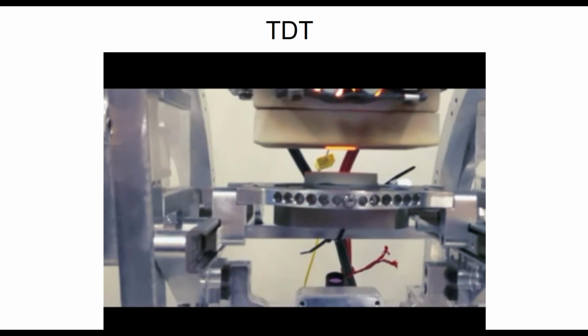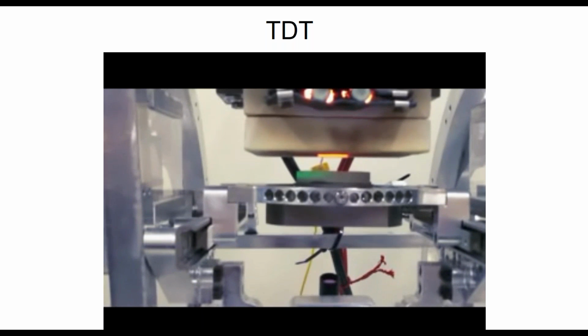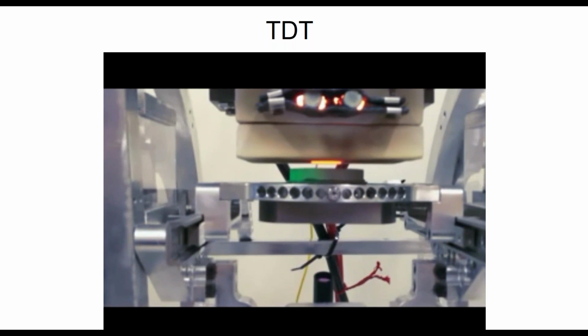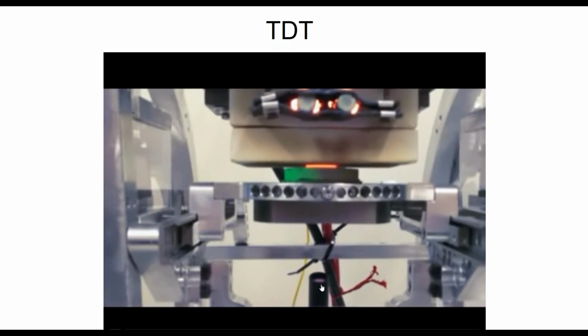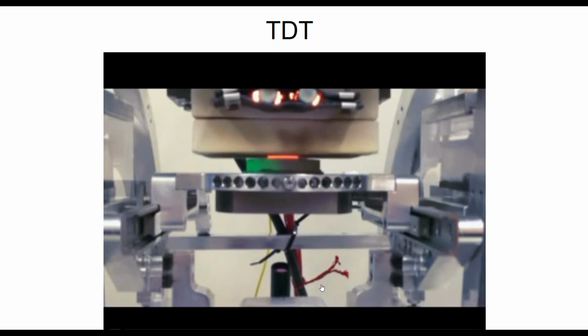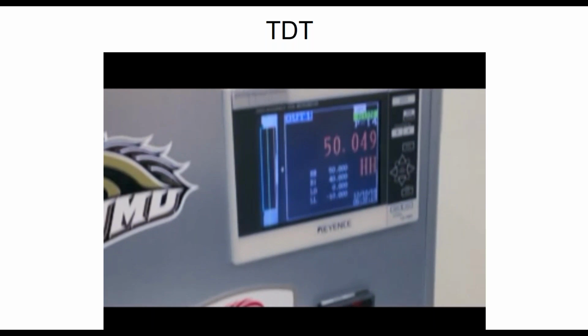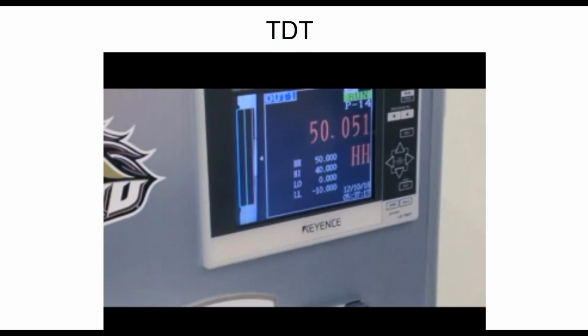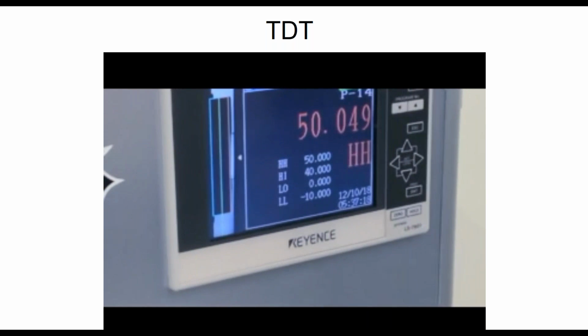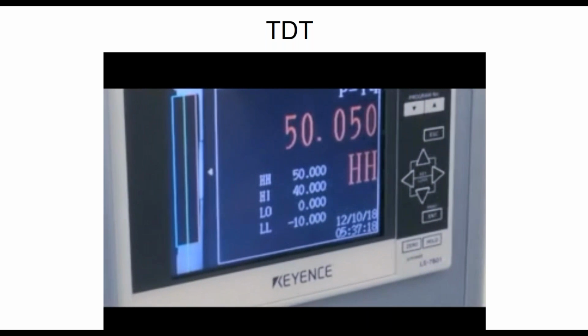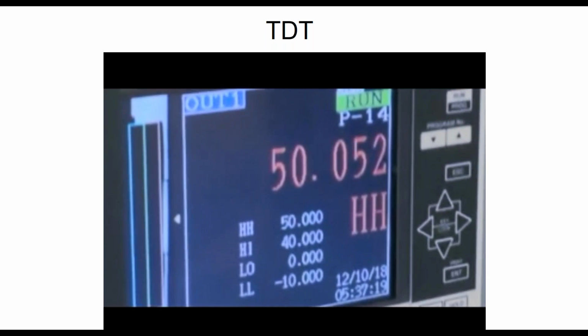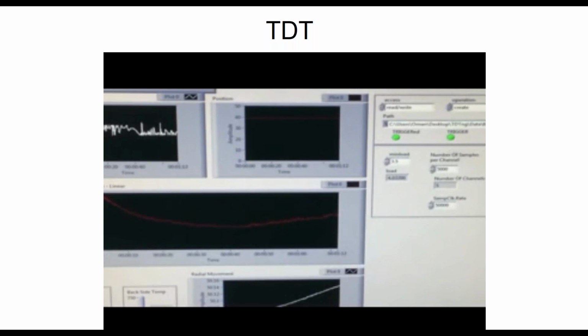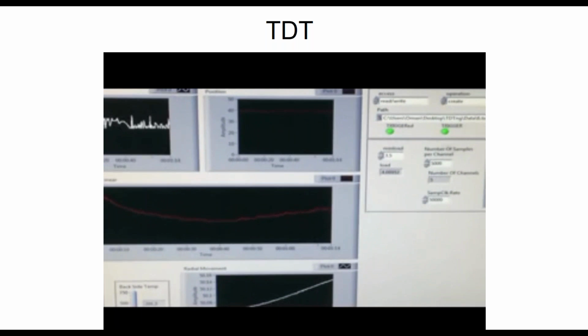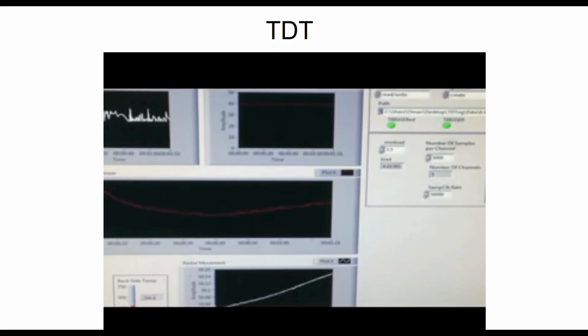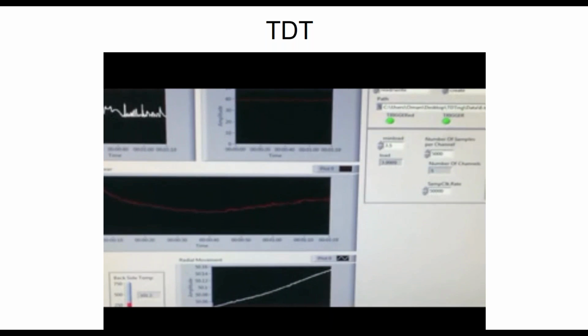So this is a semi-automated test at this stage. The specimen is brought in direct symmetrical contact with a hot surface. While we monitor temperature at the bottom, there's a sensor right there that tracks the temperature gradient from hot to the backside. And then we can look at the specimen in 3D as it expands radially. It's 50 millimeters nominally, and then it's expanding here in real time. We also measure what is happening axially, and as well, as I mentioned, the thermal issues, and we're getting that data 3D in near real time.